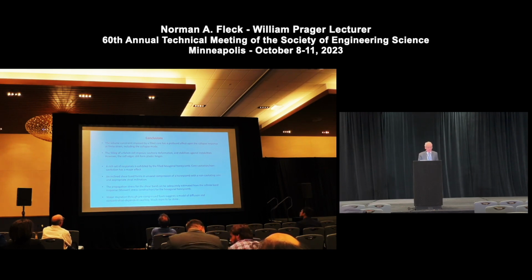Okay, so this takes me to my last slide, just to list the main conclusions of my talk, which are that filling of a core, even with a liquid of no strength, can impose a huge effect upon the response. That's particularly true for the hexagonal honeycomb when the nodal connectivity of 3 was close to the transition value of 4. When you add water and constrain the volume, you essentially reduce the degrees of freedom in the system, and the structure may now have to deform by stretching as well as instead of bending.